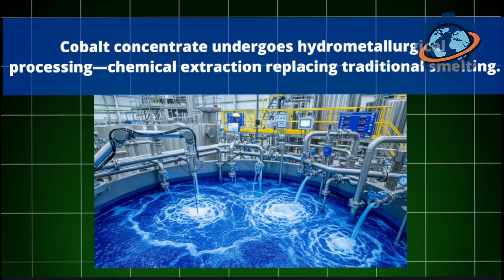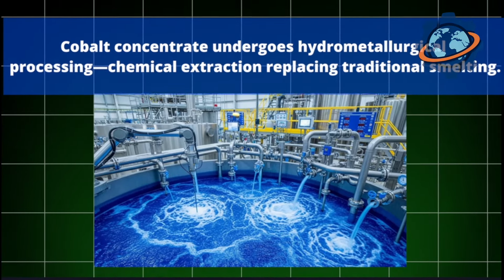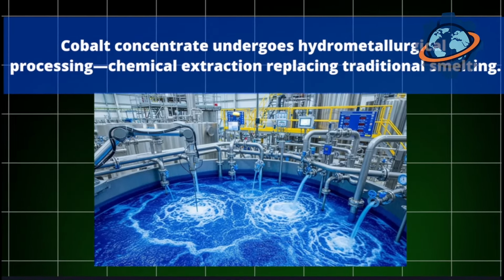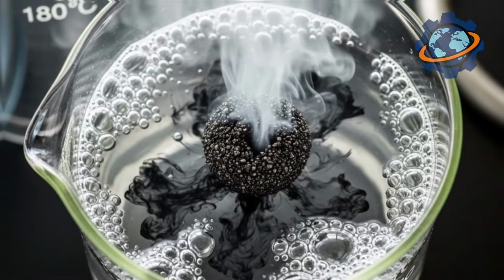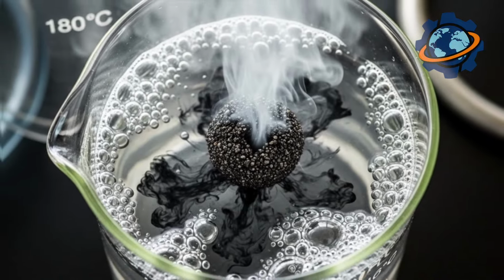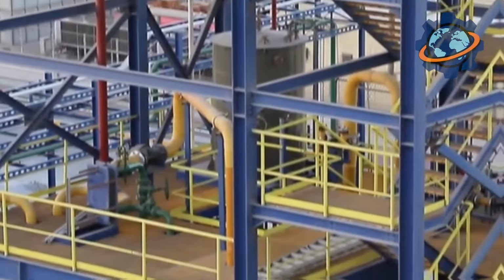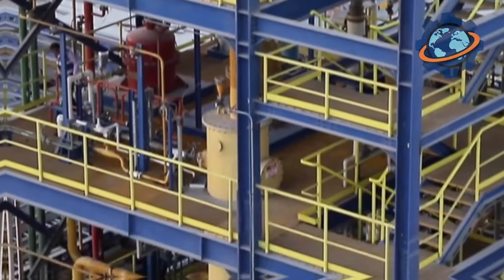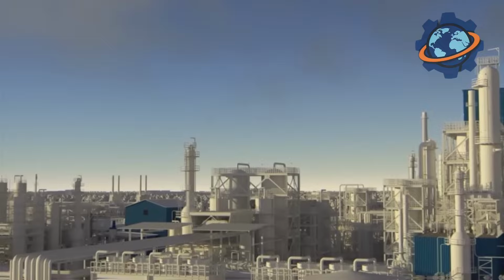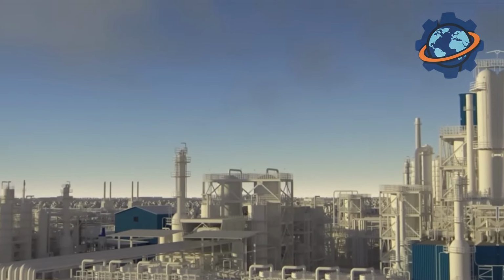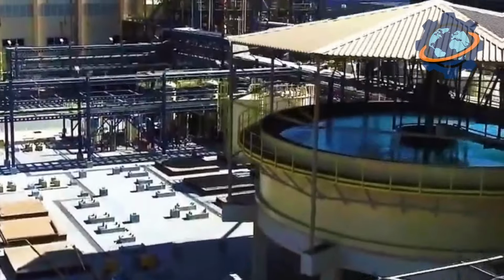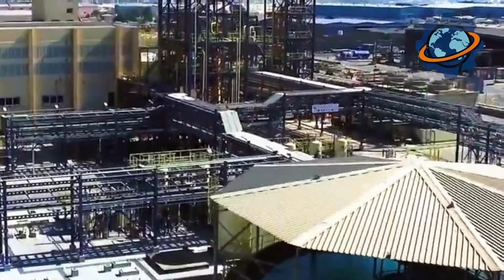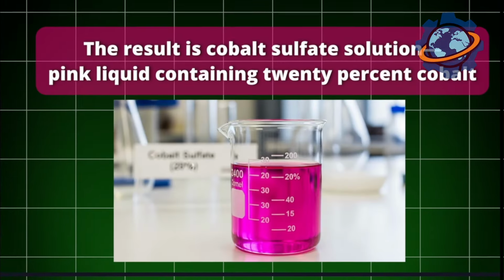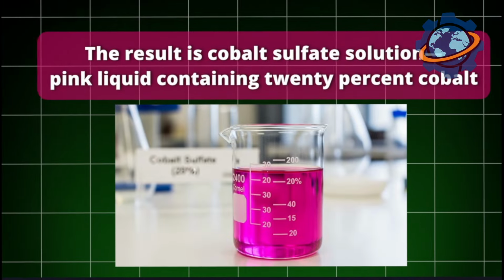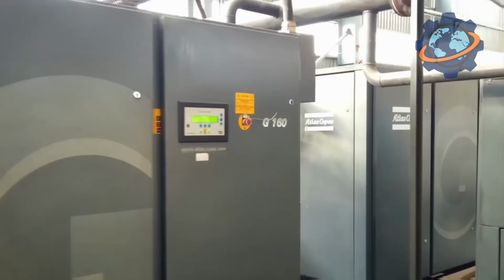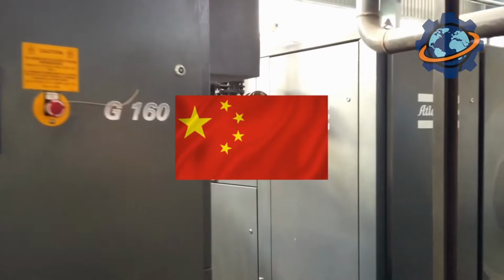Cobalt concentrate undergoes hydrometallurgical processing. Chemical extraction replacing traditional smelting. The concentrate dissolves in sulfuric acid at 180 degrees. Copper precipitates first through pH adjustment, then cobalt gets separated from nickel and manganese through solvent extraction, organic chemicals selectively binding cobalt ions. The chemistry is precise, requiring exact pH, temperature, and reagent concentrations. The result is cobalt sulfate solution, pink liquid containing 20% cobalt. This solution ships to refineries, mostly in China, where final purification occurs.